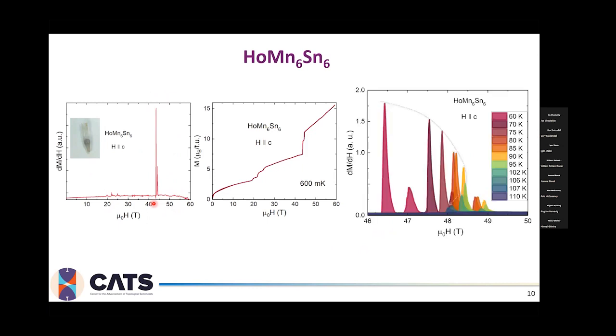And when I zoom in on that region, on that peak around 45 Tesla, and look at how it changes with temperature, we can clearly see that both of these peaks are always very sharp and very well defined, and just become smaller and smaller as I go towards the higher temperatures. And finally, it disappears around 108 Kelvin.